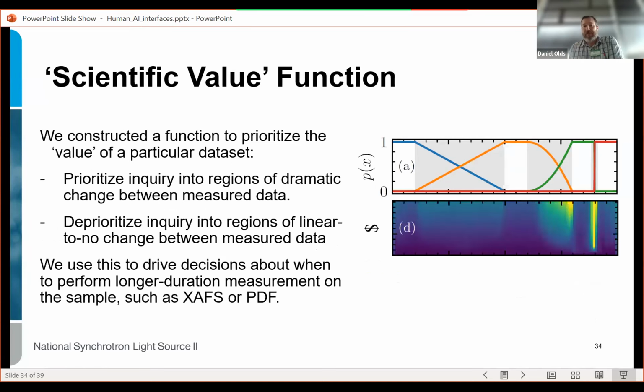For the slower measurements, driving the PDF and the XAFS, we did have a slightly more clever function. I can't share the details of it with you yet, but we call it the scientific value function. It effectively prioritizes inquiry into regions of dramatic change in the measurement data and deprioritizes inquiry into regions of linear or no change, with the thought being things that aren't changing aren't interesting and things that are linearly changing are too easy to model. So let's go to the regions that don't fit that.